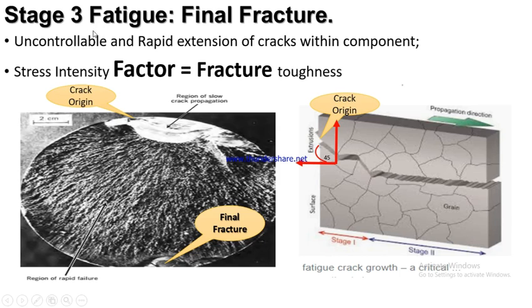So the third part, stage 3 fatigue crack, is the final fracture of the material. Like I said, there is an uncontrollable and rapid extension of the crack within the component, especially when it has propagated, and the stress intensity factor is equal to the fracture toughness of the material. In stage 3 of the fatigue, we begin to see an uncontrollable extension of the crack within the component, which we have already explained from the profile of crack growth rate versus stress intensity factor according to Paris law.